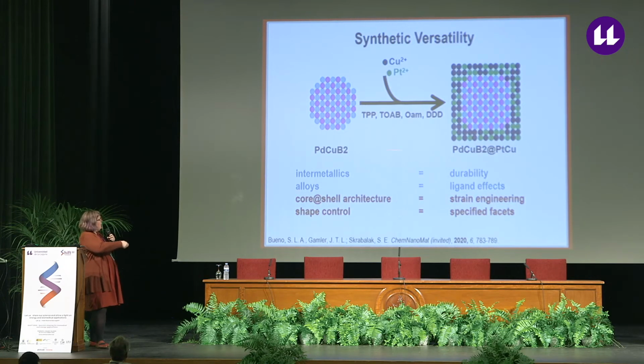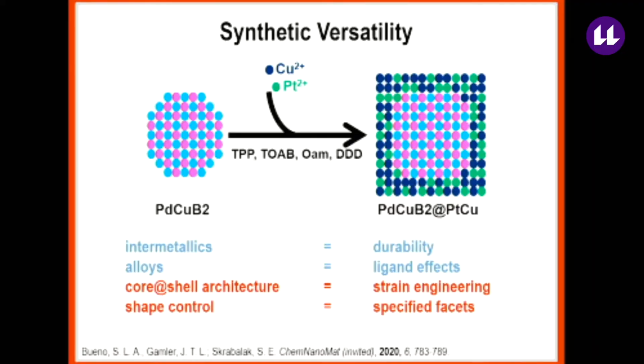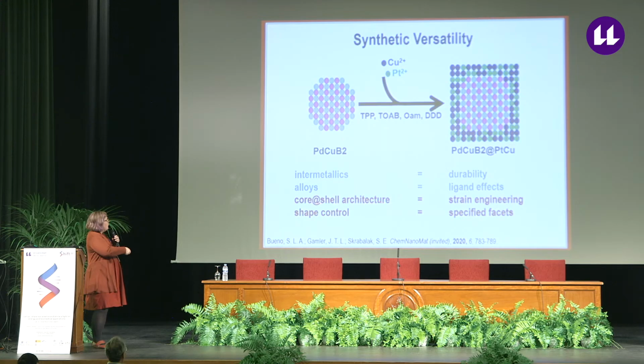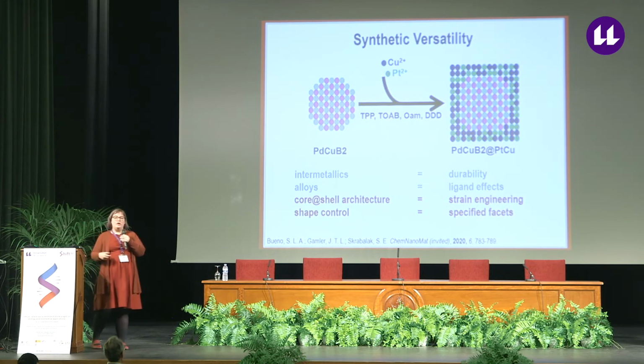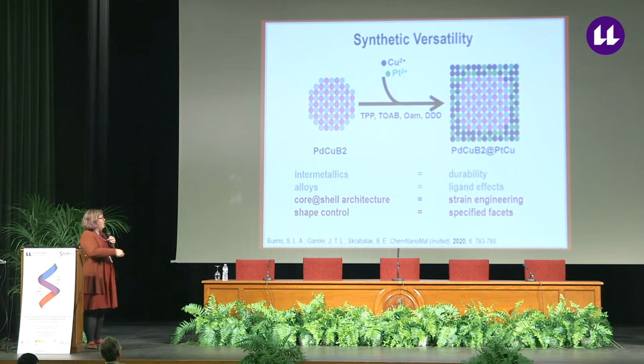And the overall motivation behind this is listed here, where the intermetallic core should impart durability because of the ordered heterometallic bonding. The alloyed surface could provide ligand effects or charge transfer on the surface so that you could modulate the electronic structure for efficient catalysis. We were excited about the core shell architecture because it allows for strain engineering imparted by the lattice mismatch between our core composition and our shell composition. And then if we could get shape control, that'd be cool as well because we'd be expressing specific facets. So this then provides a highly modular platform for the design of catalytic materials.